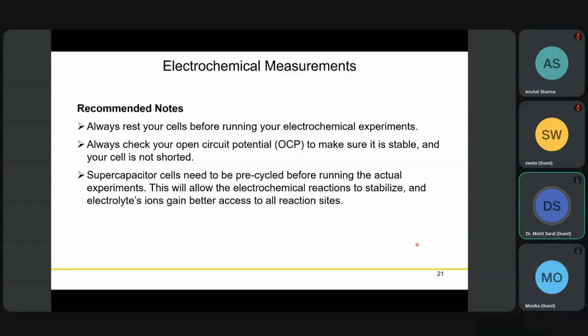When you do electrochemical measurements, let's say your material and electrolyte are ready and everything is prepared, it is always recommended to rest your cells before the experiment. What this resting does is allow wetting of your electrode, which is important. We have electrode and electrolyte in an assembly, so the electrode should be properly mixed and the electrolyte should access all the sites of your material. That is why this resting is very important. Typically 30 to 60 minutes for many double layer capacitive materials should be enough.